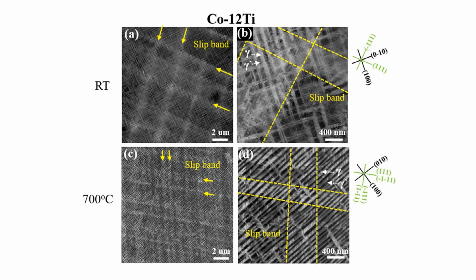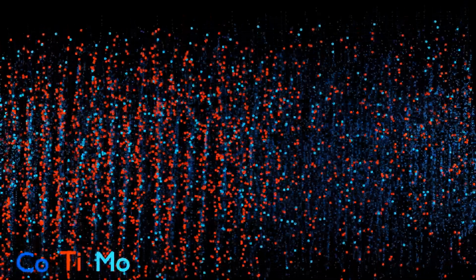These effects are due to a reduced gamma channel width and substantial hardening effect of intermetallic gamma prime cobalt, titanium, molybdenum phases in the ternary alloy, as well as due to the large shear modulus difference between gamma and gamma prime.